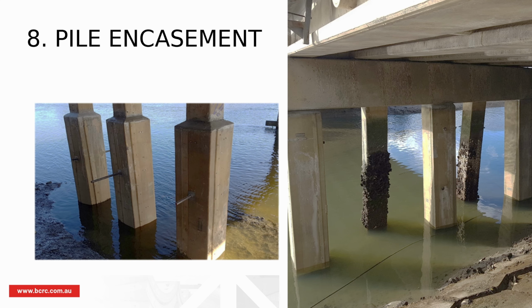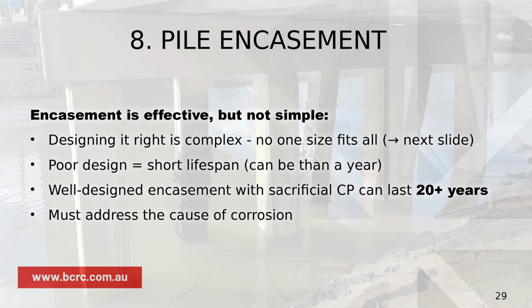On the other side, these are some jackets which are not perfect, but doing a much better job. They do extend all the way, slightly below the low tide, and protect the most vulnerable section of the piles. Encasement could be very effective, but it's not simple. Designing it right could be quite complex. I'll talk about it on the next slide. One mistake could actually shorten the lifespan of the pile quite significantly, while a well designed one with sacrificial cathodic protection could give you another 20 plus years of lifespan.